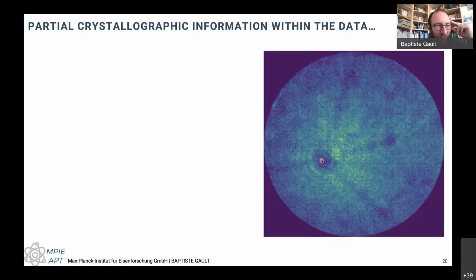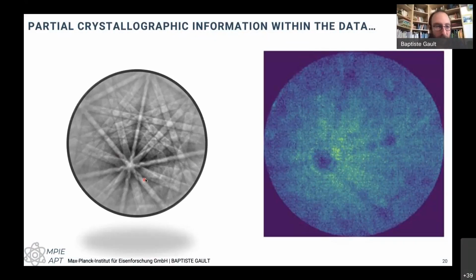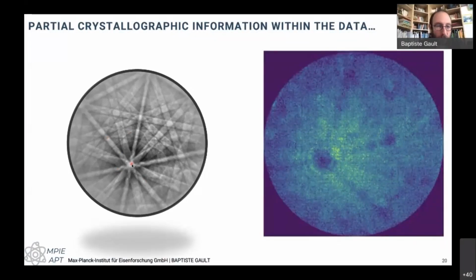So as I said, we have some trajectory aberrations. It means that when we look at the distribution of the atoms on the detector, we see a pattern forming that corresponds to where we have some of these terraces forming. I'll go into some more details afterwards. But this might remind you of a pattern that you might have seen in the past, like these Kikuchi bands that we often see in the TEM or in electron backscatter diffraction.